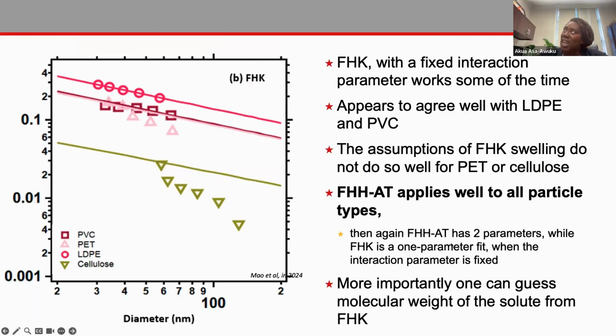Well, when we look at FHK, and for this paper, we assumed a fixed interaction parameter, that is a chi of 0.5. It appears to agree well, this polymer theory, for LDPE and also for PVC. For the lower hygroscopicity materials, such as PET and cellulose, we get more deviation from this theoretical FHK line, right? Okay, so it's not so great.